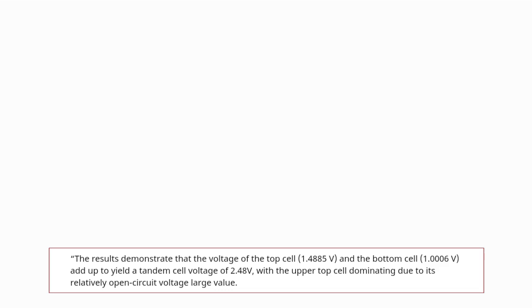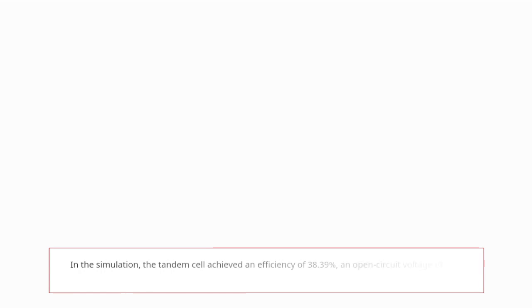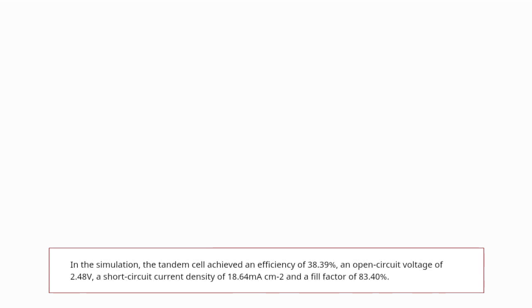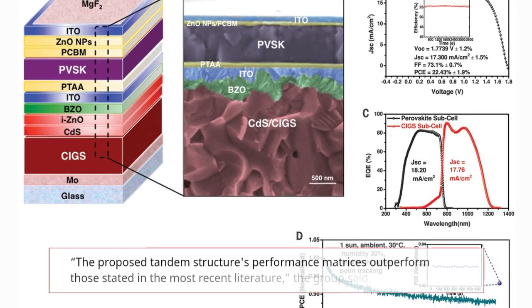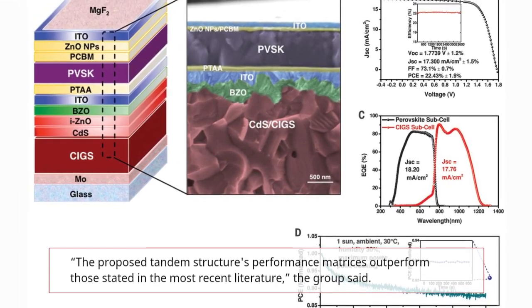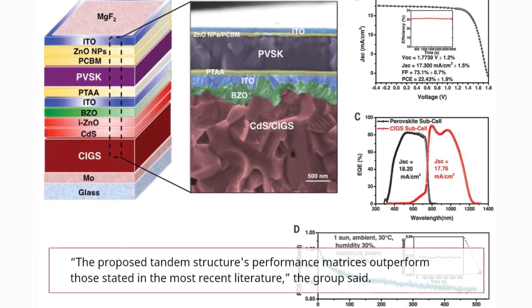In the simulation, the tandem cell achieved an efficiency of 38.39%, an open circuit voltage of 2.48 volts, a short circuit current density of 18.64 mA/cm2 and a fill factor of 83.40%. The proposed tandem structure's performance metrics outperform those stated in the most recent literature, the group said.